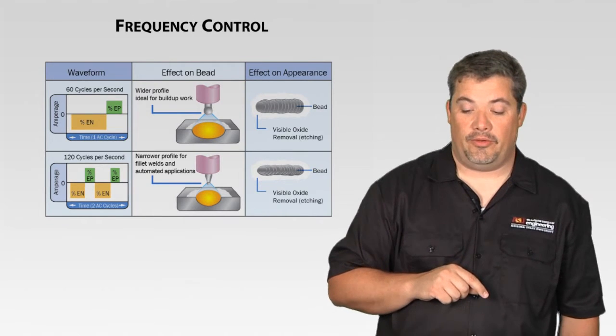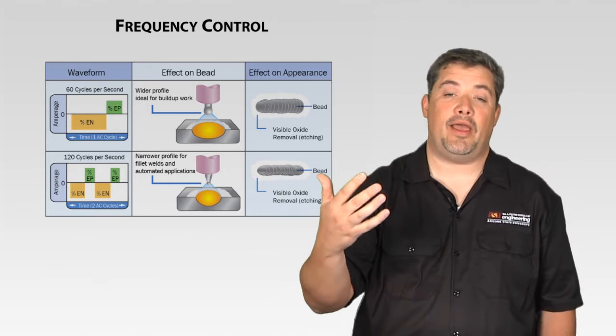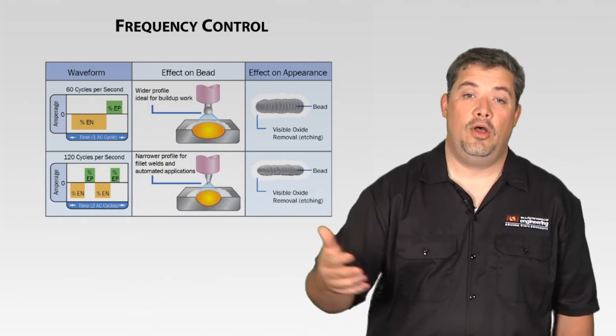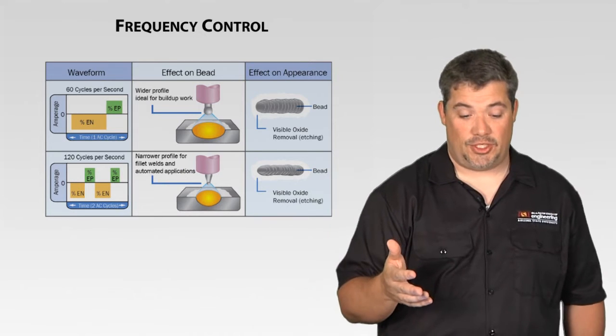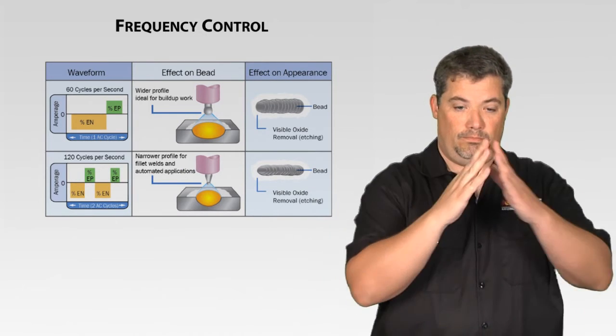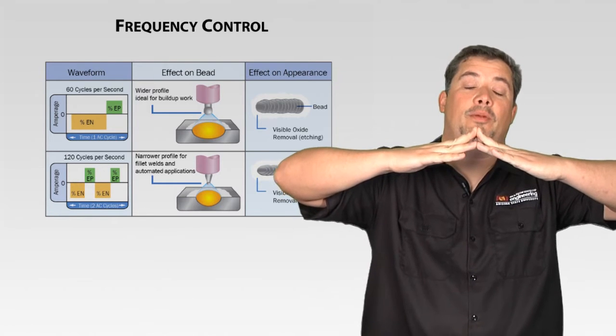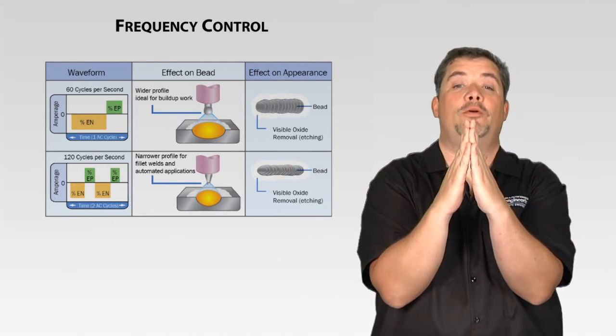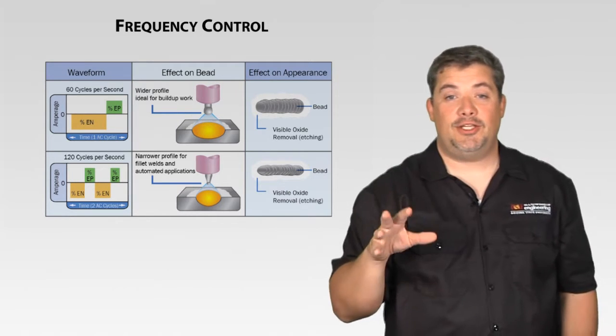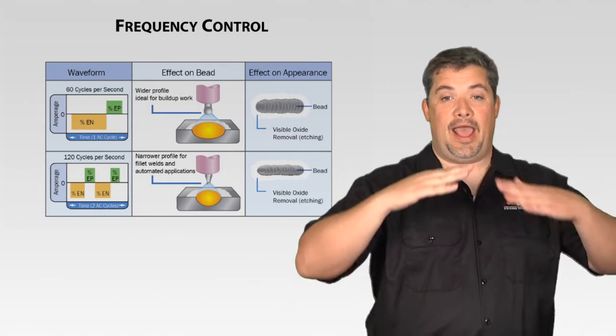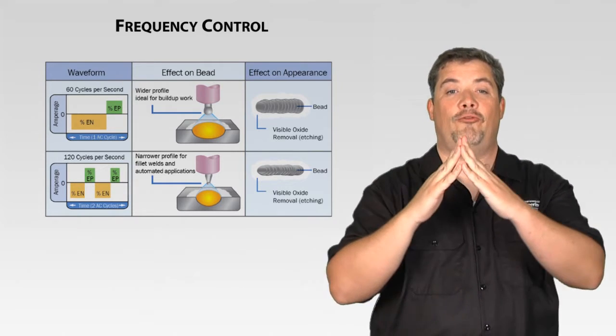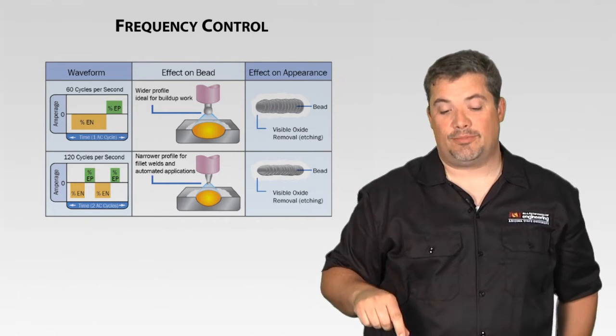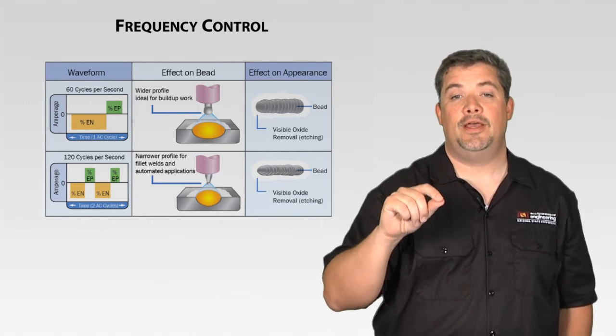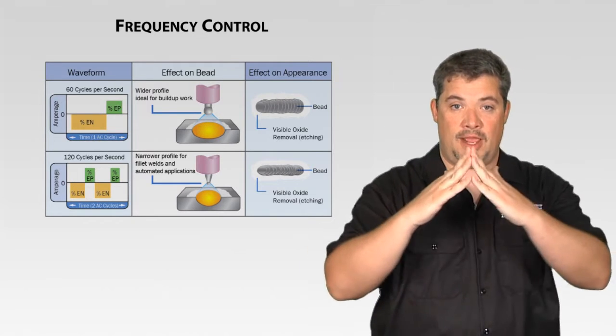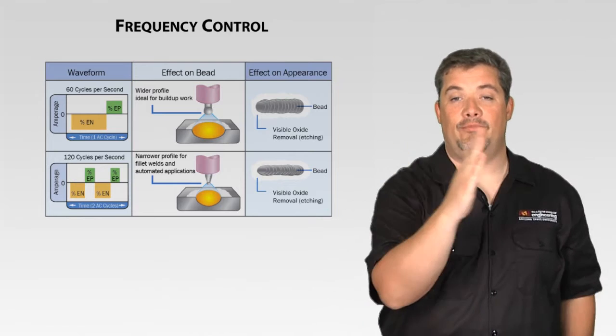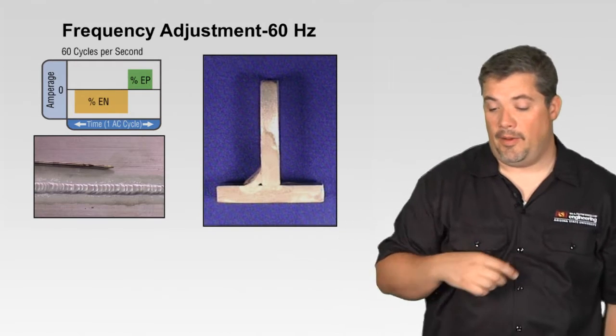I have frequency control now. Now, instead of my machine being limited to my operating frequency of 60 hertz that comes out of the wall, or 50 hertz in Europe, I can actually take this machine and I can go down to 20 hertz, which will widen that arc significantly. I can go all the way up, depending on the machine, up to 400 hertz, which will actually focus that arc significantly. So by changing the AC frequency on the output of the machine, I can have a huge effect on my bead shape and profile and the control of that arc. So frequency is probably the easiest and quickest way to see a big change in shaping that arc or bead shape. That electrode positive and electrode negative balance is another way to control that arc.